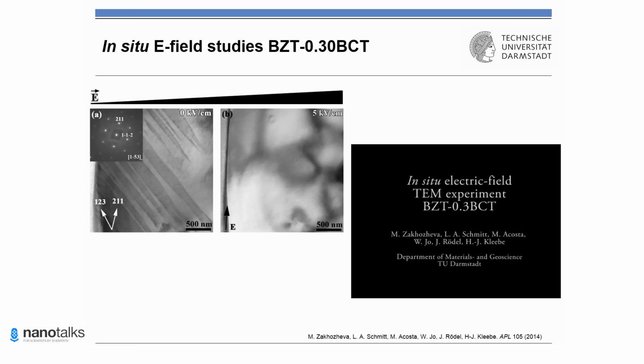Okay, I'm going to show you some results. Here you can see the rhombohedral BZT-0.3BCT composition. At the initial state, you can see a lot of lamella domains in a needle shape, which are very typical for a rhombohedral type of material. When we increase the electric field up to 5 kV per centimeter, in the direction of the field you can see here, a transformation from the multiple domain state to the single domain state occurs. You can see that the whole grain becomes one single domain.